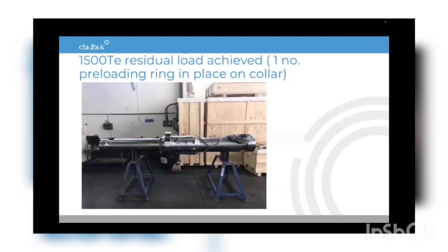Next one, please, Paul. This is a photograph of the connector fully made up, with the preload already in the connector. So during the makeup process, we would apply about 2,000 tons, and once the connector's made up, we're left with a residual load of approximately 1,500 tons. That additional ring there you can see on the left-hand end of the collar is part of the installation device. A completed connector does not have that in place, but that's a nice photograph showing a very shiny connector before it gets heat treat, subject to temperature and pressure fluctuation activities.